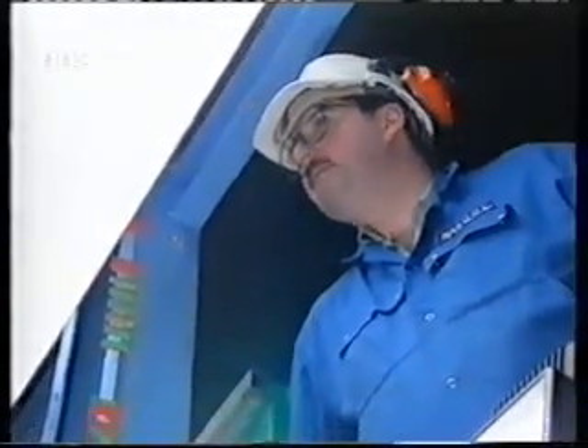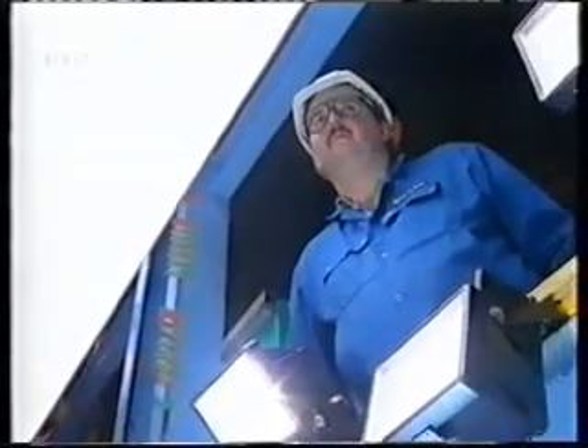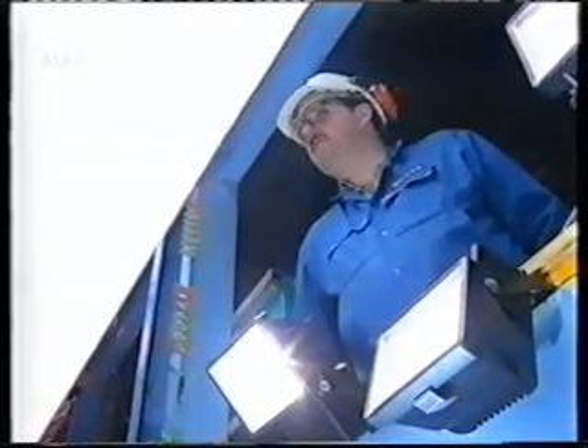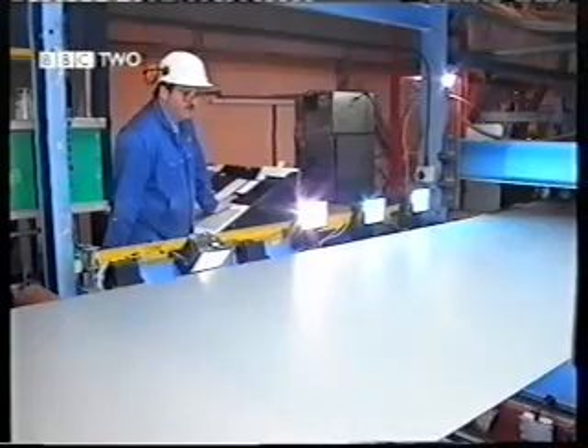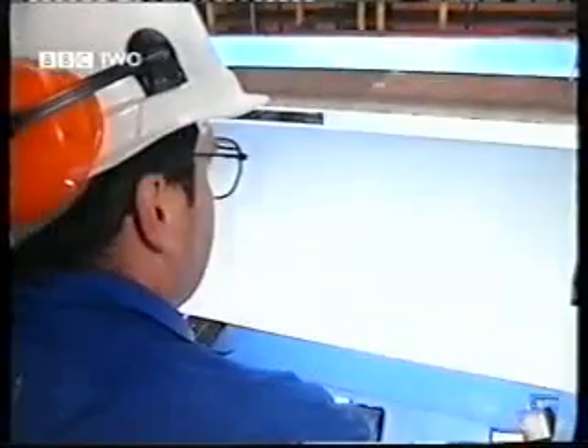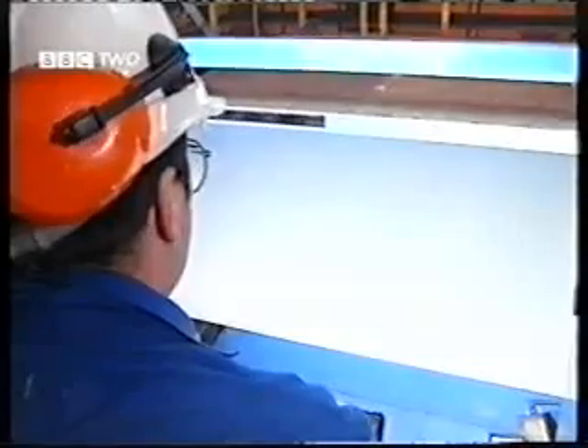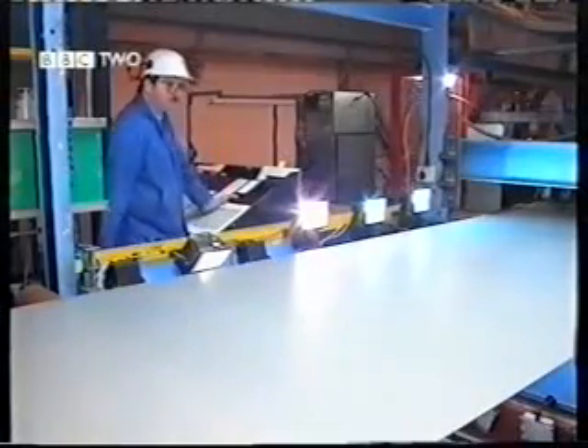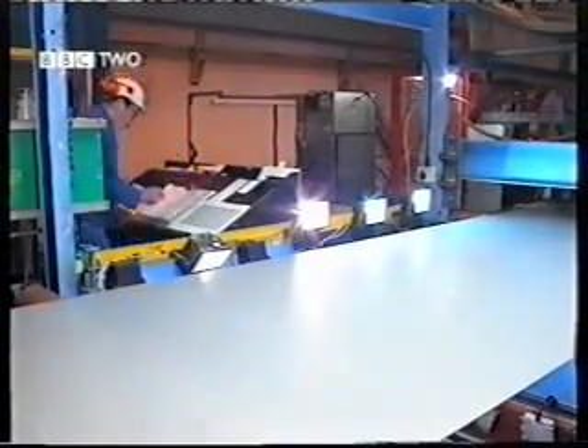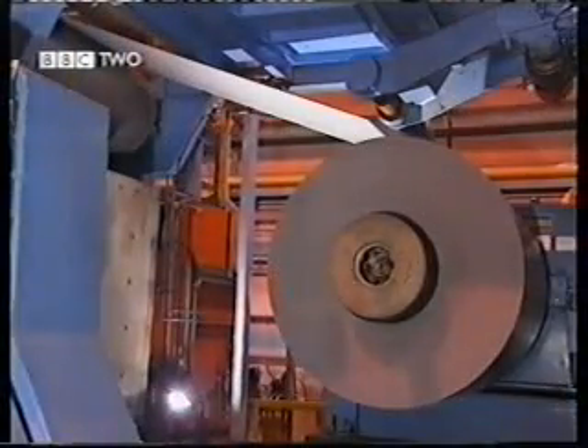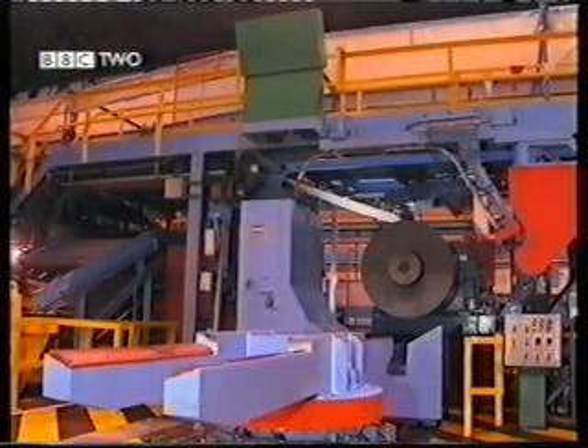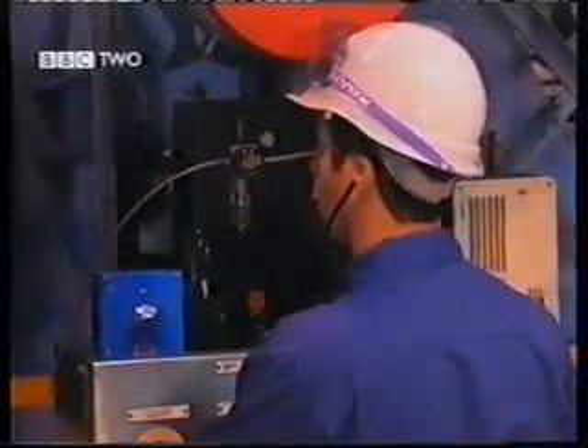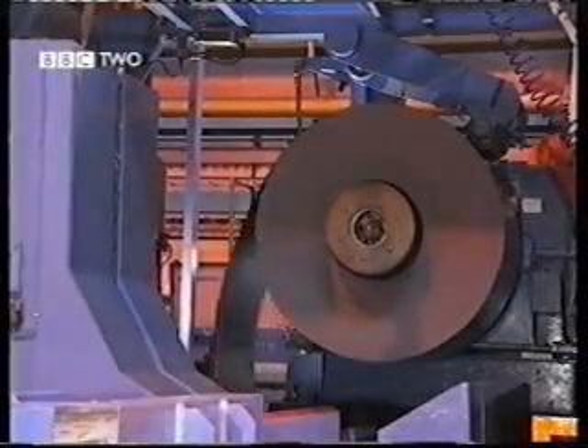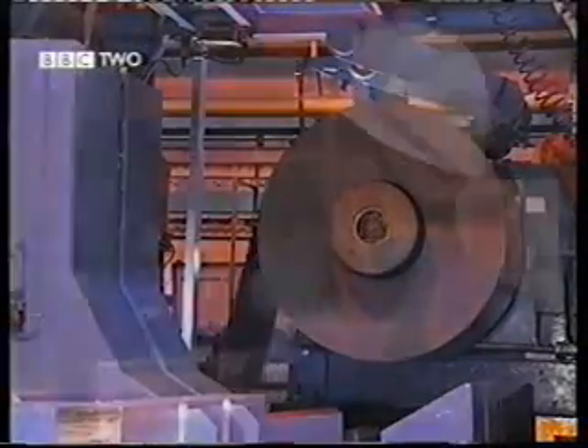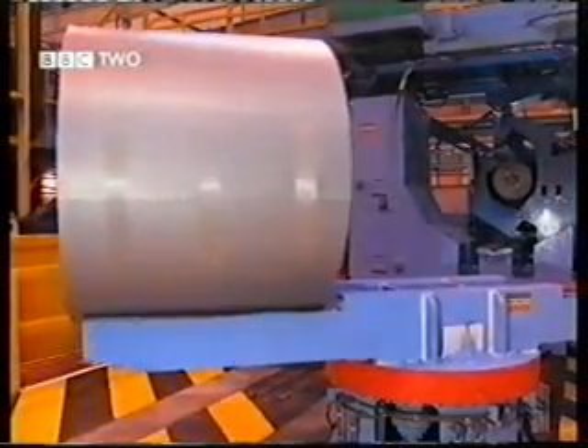The whole sandwich of zinc-nickel alloy, chromate layer and polymer can be of the order of 5 microns thick, giving the same protection as the alternatives whose coatings are a little thicker at between 6 and 8 microns. Now this may not sound much of a difference, but the thinner the coating, the easier the material is to work with. The main disadvantage is it's the most expensive of the coated steels. Despite this, it is used quite extensively within the automotive industry. So the cost equation is not always the limiting factor.